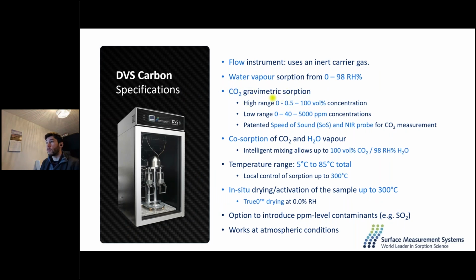There's a high range, so from 0 to 100%. There's also a low range of concentration, so a ppm level. So this can be applied both to direct air capture or post-combustion applications. Now, since it goes up to 100% pure CO2, it can also be applied to edge cases like desorption. Water vapor can be generated in the range from 0 to 98%, and of course both of them can be mixed to have a stream that contains both CO2 and water in different levels.